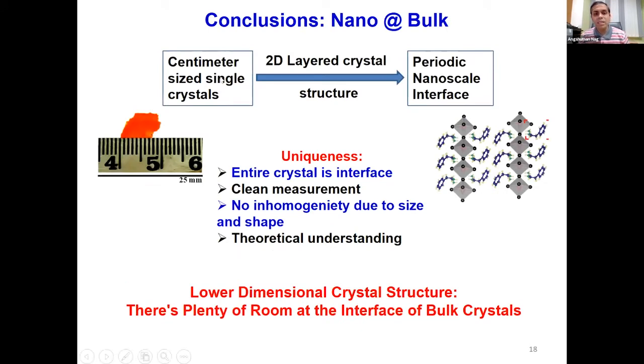So today what I discussed is the properties of centimeter size crystals that have a layered structure. Because of this layered structure, there is a periodic arrangement of nanoscale interfaces, and these nanoscale interfaces give rise to interesting properties at the nano level. So the interesting aspect is that the entire crystal is the interface. If you're looking for properties that come from the interface, like dielectric confinement or chiral optoelectronics, etc., they'll have a more prominent role in this kind of crystal that is full of nanoscale interfaces.